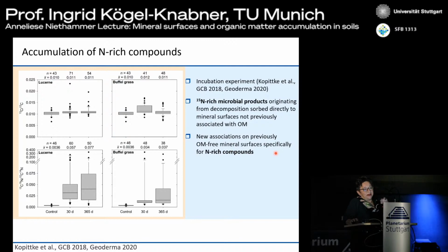And this is where we find specifically these nitrogen-rich compounds. And so we think it's very important how the microbial habitat is and how these microbial communities can grow in soils so that they produce these organomineral associations via their exudates, via their necromass, and that this still needs three components to come together at a spot at micrometer scale. We need a mineral surface, we need organic matter that is decomposable for microbes, and the microbe must also be at the same spot to produce such organomineral associations and to make them grow.